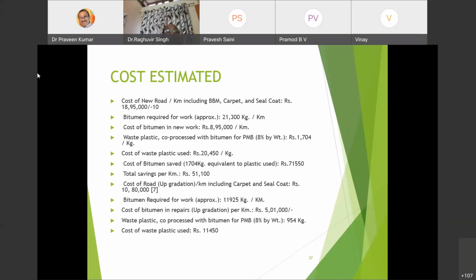Cost of bitumen in new work is Rs 8,95,000 per kilometer. Waste plastic is co-processed with bitumen of PMB at 8% by weight. The cost of waste plastic used is Rs 20,450 for the quantity used. The cost of bitumen saved, 1,704 kg, equivalent to plastic used, is Rs 71,550. So the total saving per kilometer is Rs 51,100. The cost of road upgradation per kilometer, including carpet and seal coat, is Rs 10 lakhs 80,000.